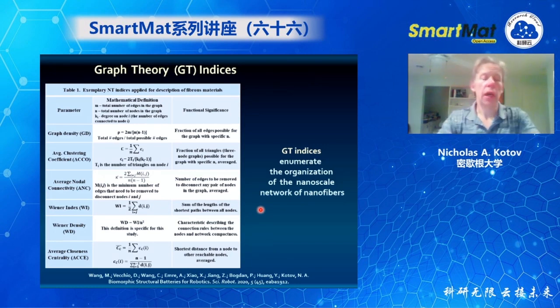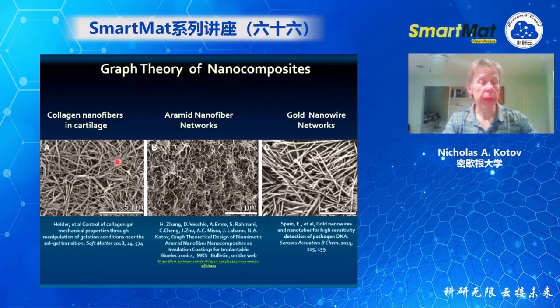And after that, we can apply network theory or graph theory to describe the organization of this network by using a variety of indices, for instance, average clustering coefficient or average nodal connectivity. All of them are describing some aspect of the structure. It may be short range or long range. Importantly, it changes from composite to composite and from network to network. So this is the organization of collagen fibers in actual cartilage. This is our aramid nanofibers. We have differences in scale, but the importance here is actually the organization of the fibers.